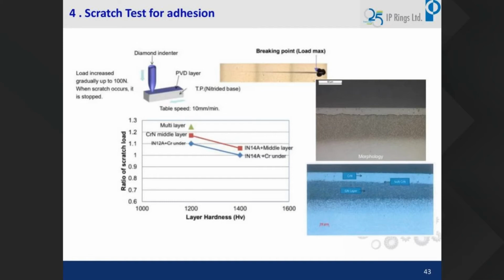In one of our projects, a Volkswagen project, we did a conventional PVD, that is nitrided PVD with chromium undercoat, and with IN14A PVD, that is chromium nitride PVD, which is of hardness 1200 to 1400 HV. In that case, we manufactured the product, and this was also for BS6 application. We struggled a lot, we learned a lot also during our journey.